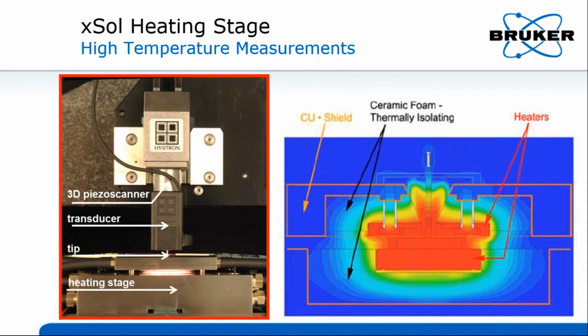The heating stage, the xSol stage, has two heaters designed to clamp the sample in the middle. The sample is under temperature control on both sides. Therefore, the temperature within the sample can be highly uniform. Moreover, the unique engineering chamber design allows to minimize the influence of environments and maximize the stability of temperature control. The minimal exposure of the sample reduces the disturbance, therefore limiting its influence to the instrument itself.